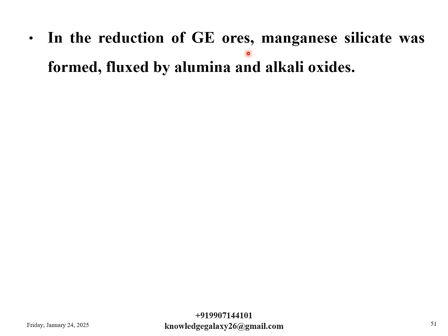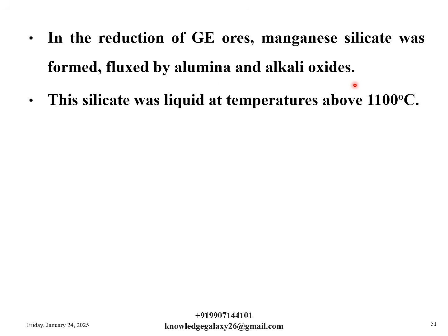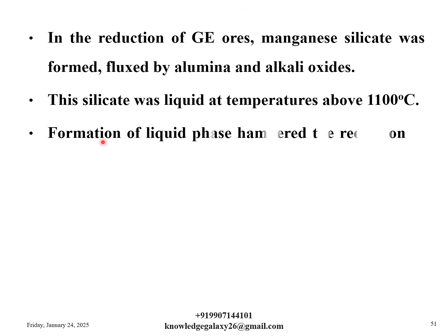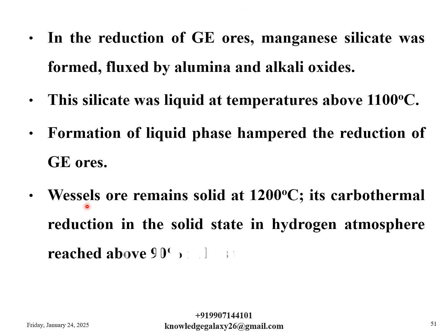In the reduction of GE ores, manganese silicate was formed, fluxed by alumina and alkali oxides. This silicate was liquid at temperatures above 1100 degrees Celsius. Formation of liquid phase hampered the reduction of GE ores. Wessels ore remains solid at 1200 degrees Celsius. Its carbothermal reduction in the solid state in hydrogen atmosphere reached above 90% in less than 20 minutes.